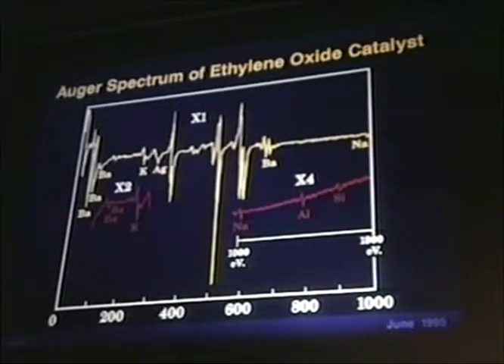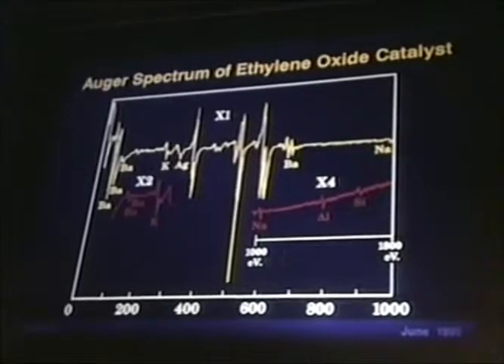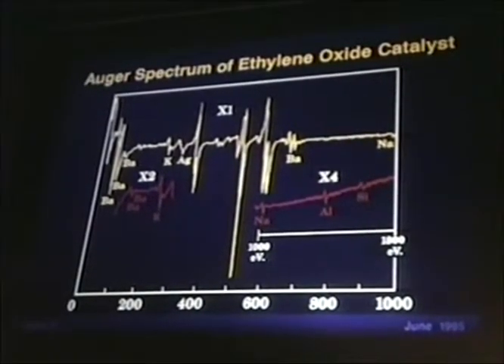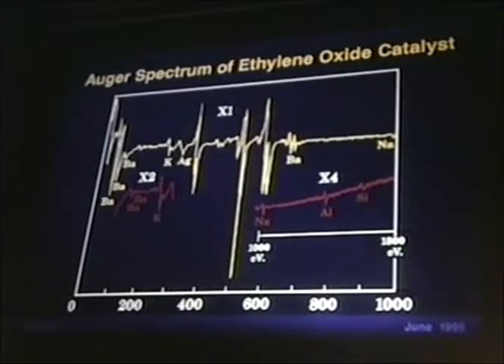These elements are the components of the catalyst support used in the manufacture of silver catalyst, along with potassium. The surface concentration of these other elements, when we did extensive statistical regression, were found to be also inversely proportional to catalyst activity, and hence directly proportional to the potassium. In fact, the slide that I shared with you previously, showing the inverse correlation, gives an even better straight line if you include just the sodium along with it.